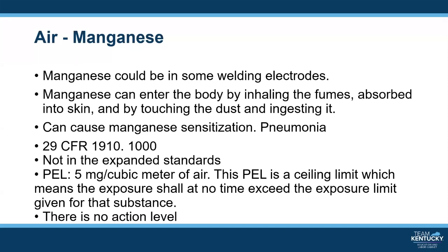OSHA regulations on manganese are found in 29 CFR 1910.1000. Manganese is not in the expanded standards. There is a regulation on manganese exposure, which is 5 milligrams per cubic meter of air. This permissible exposure limit is the ceiling limit, which means that the exposure shall not exceed this level at any time. There is no action level for manganese.